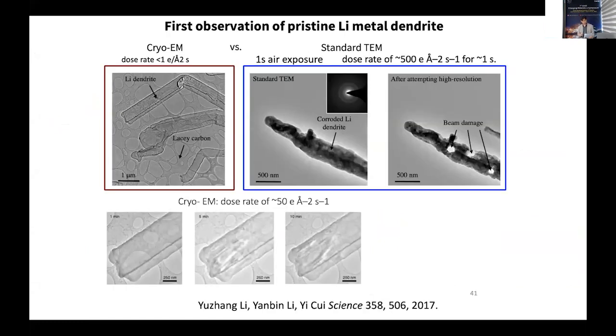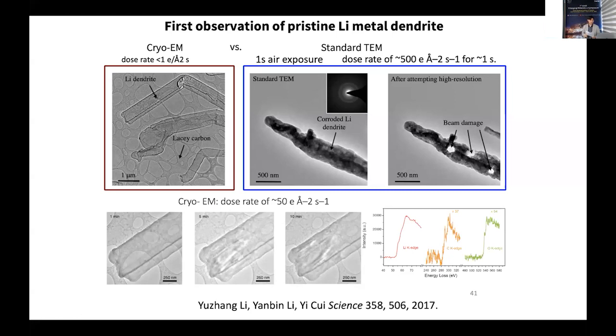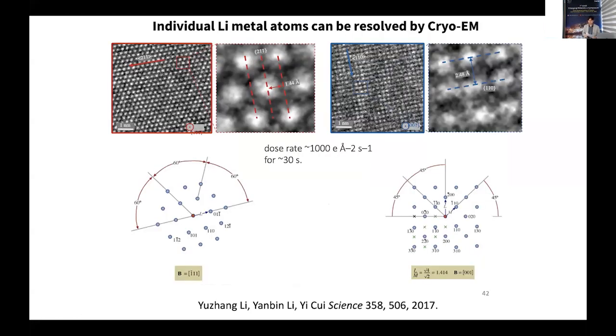So using the cryo-EM technique in the lab, you see we are monitoring the dose rate. For the first time, we were able to resolve stable lithium metal dendrite. In dose testing, it can last for multiple minutes. We obtained the atomic scale resolution of metallic lithium for the first time, and identified the lithium dendrite growth orientation, the crystallographic orientation. We see 3 different orientations right there. We identified why it likes to grow along certain orientations: because of the interfacial energy with the electrolyte, with the SEI, it likes to have 110 as the stable sidewall interface. So it favors a certain growth direction.